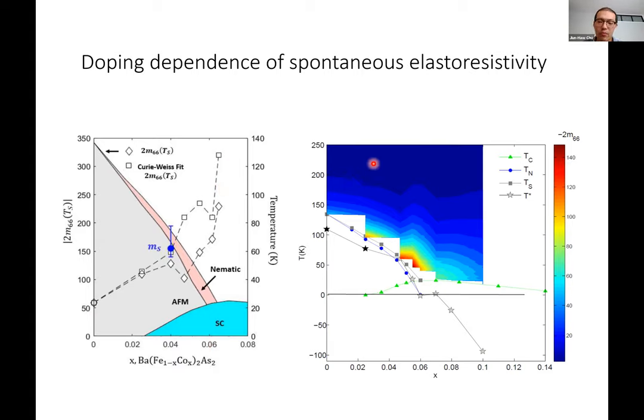So looking back to this color map, I think there's actually more information hidden within it. You can see that this elastoresistivity coefficient is really strong around optimal doping, but this is not just saying that the nematic susceptibility is stronger at optimal doping. It's also saying that the lattice coupling is enhanced. If you're considering the nematic susceptibility, it will diverge as you approach the critical temperature. So naively, you would expect to see the same intensity going from the underdoped side all the way to the overdoped side. But still you're seeing the intensity increase as you move toward this phase boundary. So I think that basically means that there's a combination of divergent susceptibility, but also a divergent electron lattice coupling.